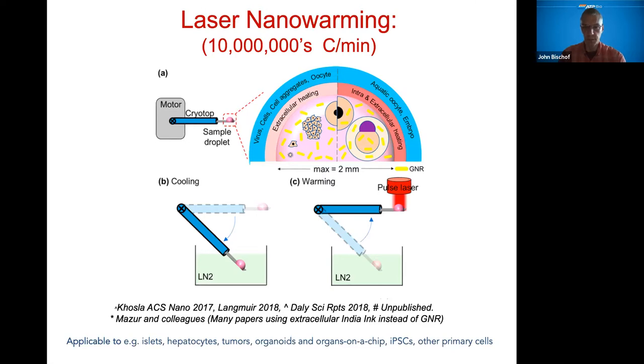He tried it many times. And so what we did was, if you try to put India ink into one of these embryos, it's basically toxic. So that's a no-go. So we shifted to using plasmonic gold nanoparticles. And we've been looking at this for other reasons, and a lot of other people have too. There's a huge field associated with this that most people know about in terms of nanomedicine and the use of lasers and plasmonics.